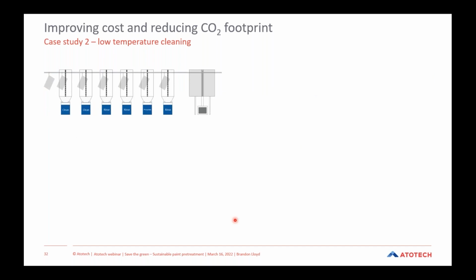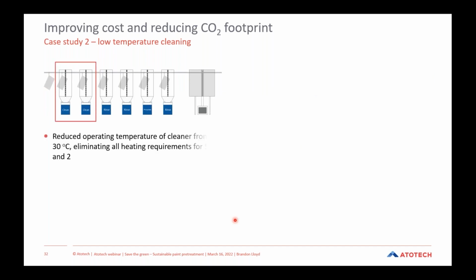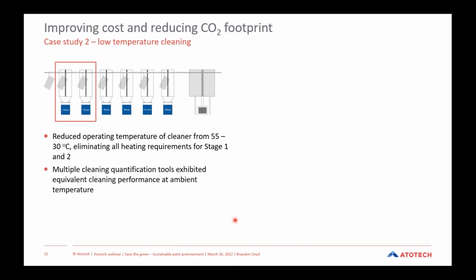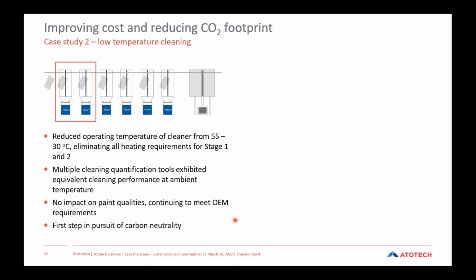So here's an example of their line setup. You can see that if we focus here exclusively on the cleaner stages, they were able to reduce the operating temperature from 55 degrees Celsius down to 30 degrees Celsius, which eliminated all of their heating requirements for both stage 1 and 2. With multiple cleaning quantification tools, they were able to exhibit an equivalent cleaning performance, even at ambient temperatures. And this had absolutely no impact on their paint qualities. And so with this, they were able to continue to meet the OEM requirements that they were achieving. And this is their first step in their pursuit for carbon neutrality.